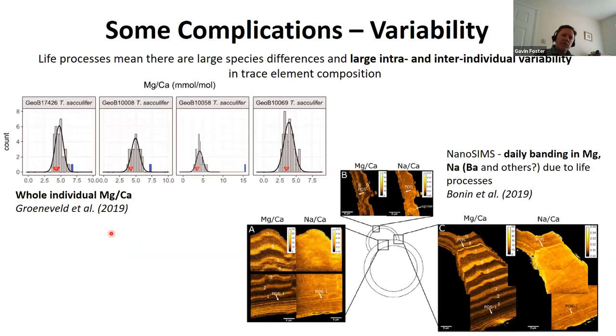So another complication that's recently come to light that limits how well we can reconstruct past climate is that there's a large intra-individual, so that's within individual, and between individual variability between the forams. This is a plot from a recent paper that shows whole individual magnesium calcium ratio of the same species from a couple of different cores. You can see that in each individual, taking a whole shell, dissolving it up and measuring it by standard ICP-MS, there's quite a range in magnesium calcium ratio, from about 2.5 or 3 to 6, let's say.